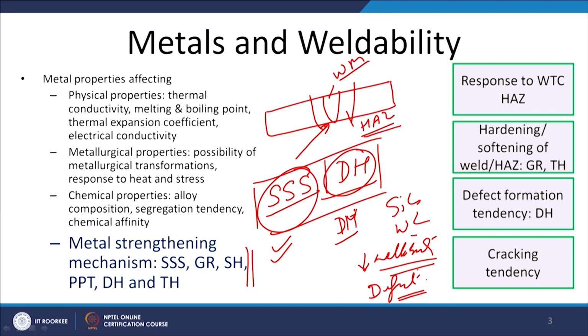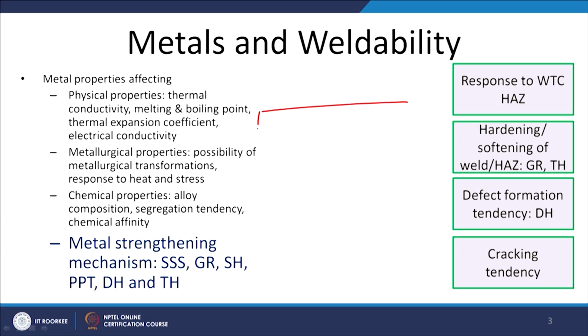Then we will have another aspect, if the dispersion hardened material is subjected to joining through a controlled deformation based approach, like friction stir welding or friction welding. In that case, there may be refinement of those dispersion particles that may lead to improvement or deterioration, as per the way by which the particles are getting affected due to the controlled deformation during the welding.